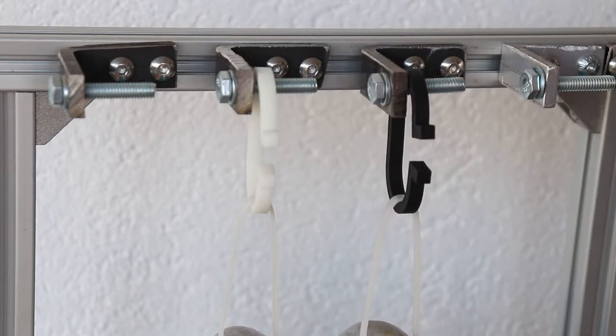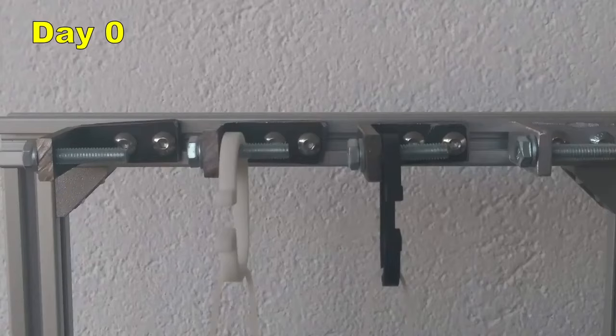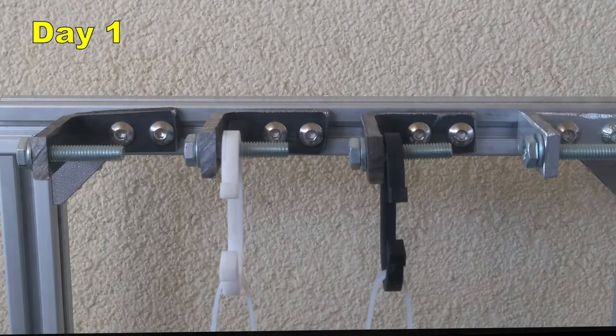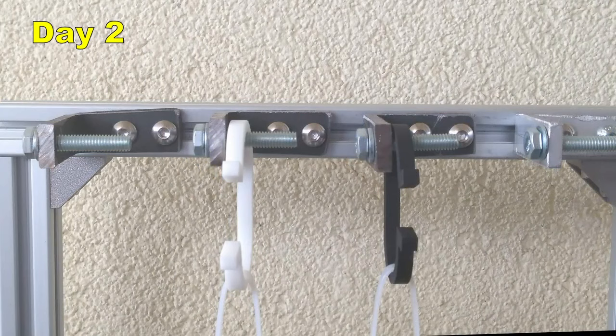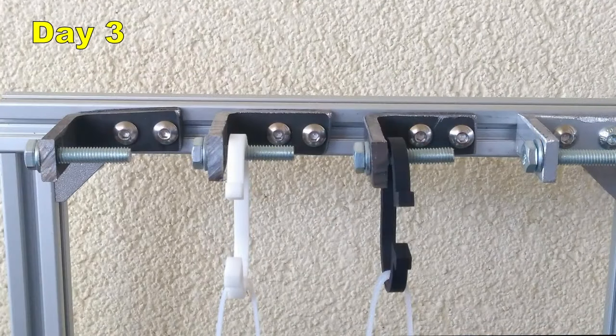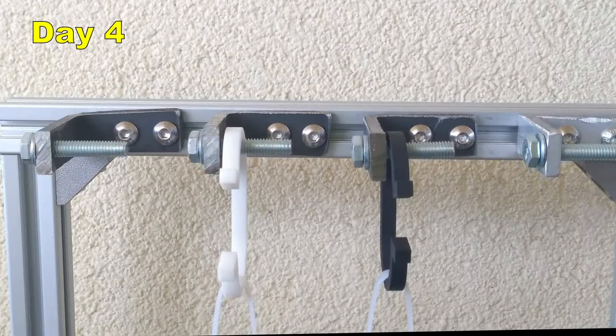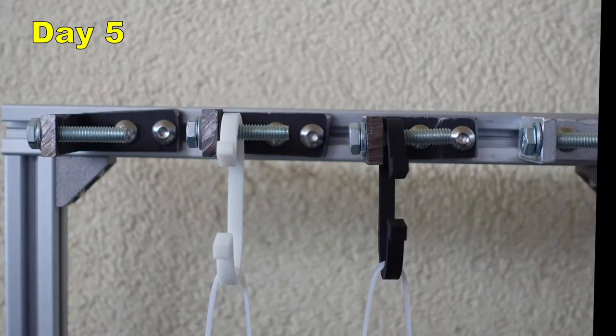And don't worry, I will do the measurements off camera, only I will create a picture once a day. This is day 0, and this is after 24 hours, quite a lot of deformation on both objects, but later the nylon stopped with the creeping until the resin continued with deformation, and now everything goes into the heated oven.